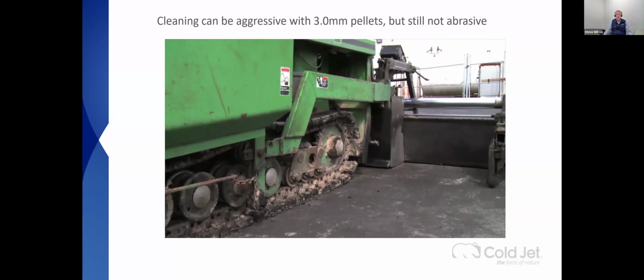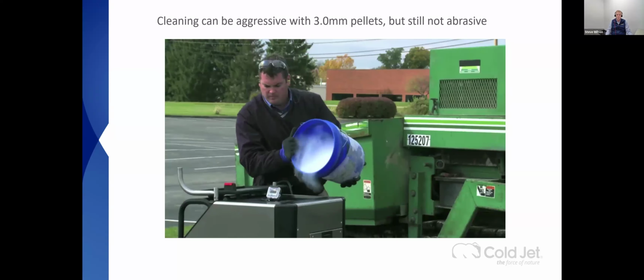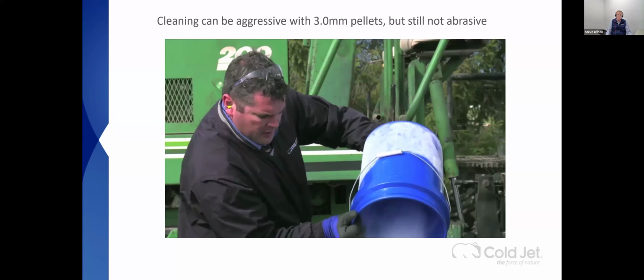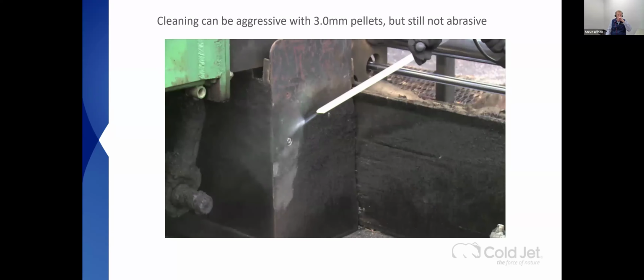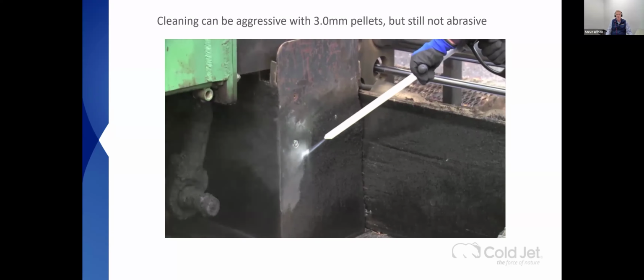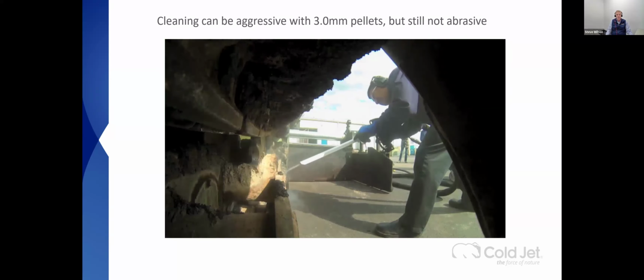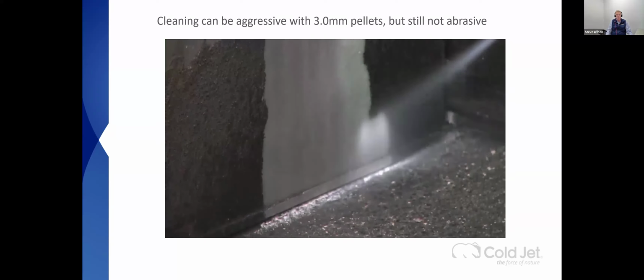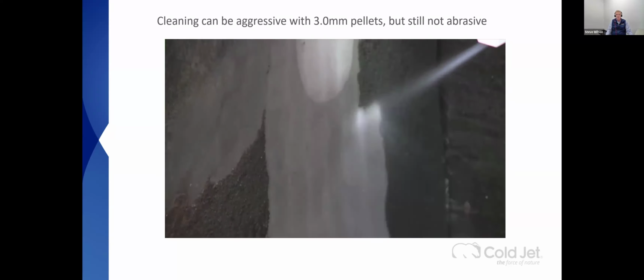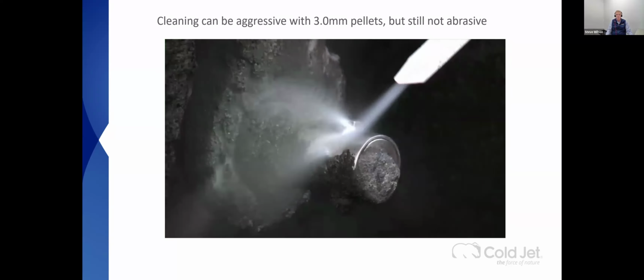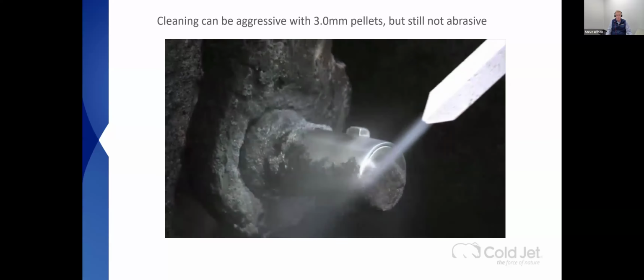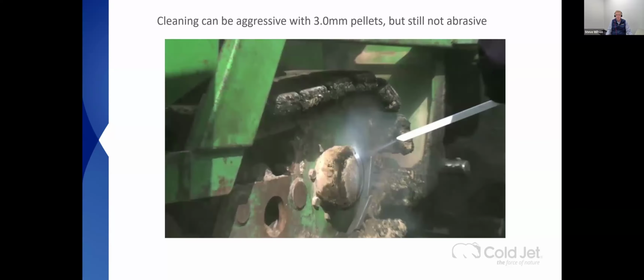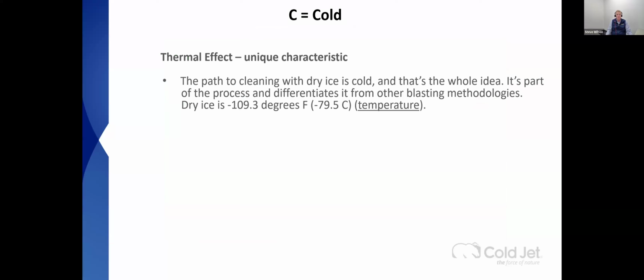For example, this is an asphalt truck, and we're going to just take 3mm pellets. We're going to put 3mm pellets in. We're just going to leave them at 3mm pellets, and you're going to get a much more aggressive, yet not abrasive clean and move very quickly. You'll note the dry ice is sublimated. It's going to a gas. It looks like the asphalt's disappearing. It is going to the ground. The contaminant does not disappear. But you can see you can be aggressive when you need to.